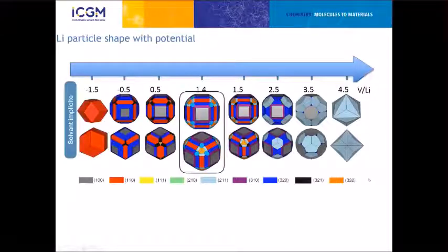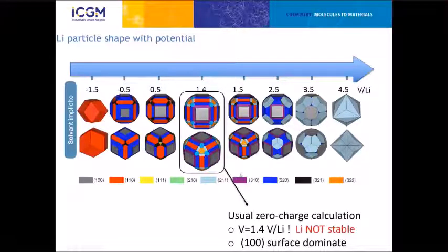So if I redo that for the last time for lithium, what I get, if I look at the uncharged system, is that the uncharged system for lithium is associated with a potential of plus 1.4 volts relative to lithium. So in fact, when you are modeling an uncharged lithium surface, you are modeling an unstable system, because at 1.4 volts, the stable form of lithium is not lithium metal, it would be lithium plus. So you are computing a system that is not experimentally possible.